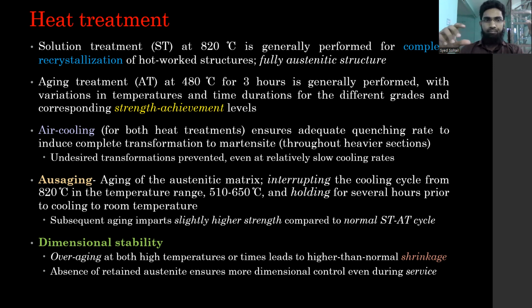and aging. Aging treatment is done at 480 for 3 hours, and the variations are there in temperature and time duration. As I mentioned, 1 hour, 2 hours, 30 minutes also is done for aging. 30 minutes, 1 hour, 2 hours, 3 hours, 5 hours, or 6 hours. Temperature is also there from 450 to 500, 550 even sometimes. These are there to achieve the different grades and corresponding strength levels, which we mentioned. You want to have certain strengths, so those are controlled with the aging schedule, aging heat treatment, time and temperatures, etc. Air cooling is done, as I mentioned, for both heat treatments.